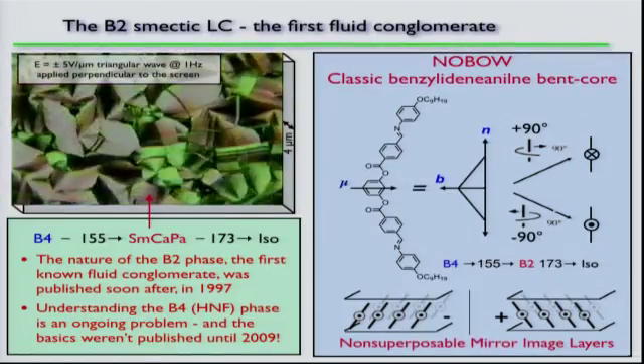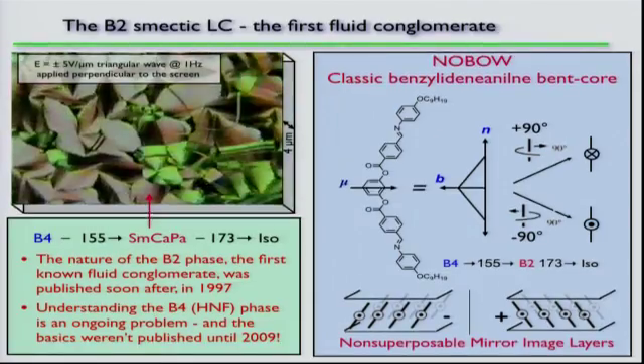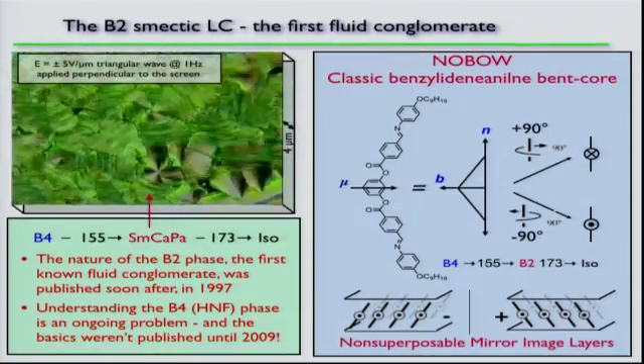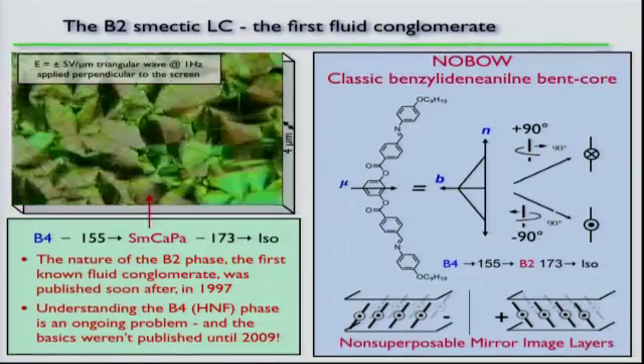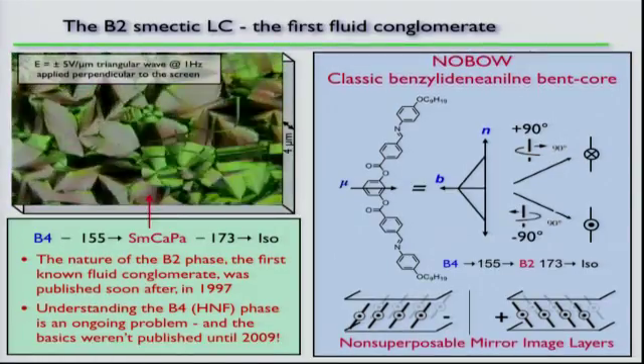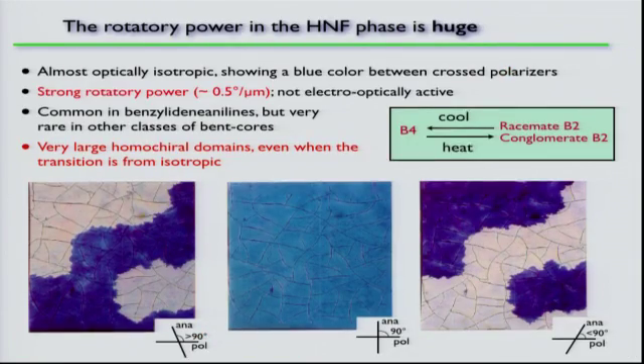So I'll try to give you an idea. Okay, so here is this beautiful chiral smectic switching coming from an achiral molecule, and you've got right-handed domains and left-handed domains, and that's the first fluid conglomerate. But the B4 is really surprising and incredible. It has this strong rotatory power, and Peter Palffy-Muhoray actually mentioned this in his talk, but I actually believe that this material has the strongest rotatory power of any isotropic fluid. The strongest, so it's like 0.5 degrees per micron.